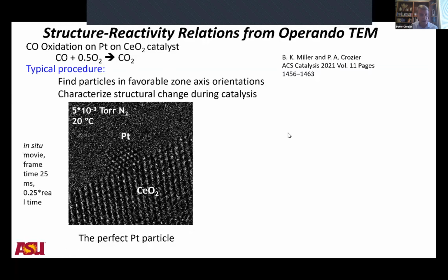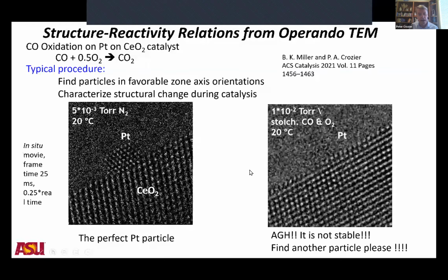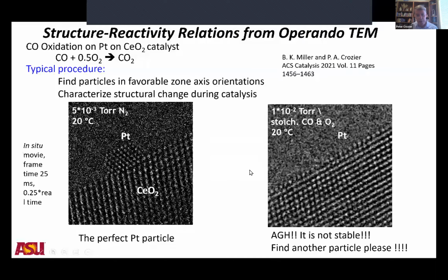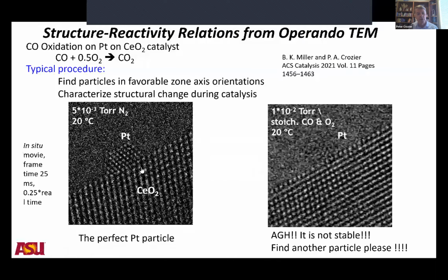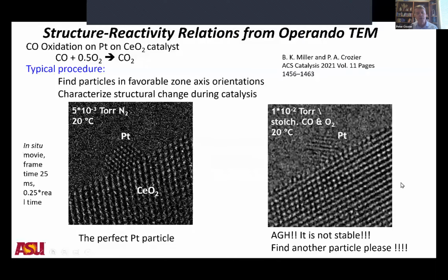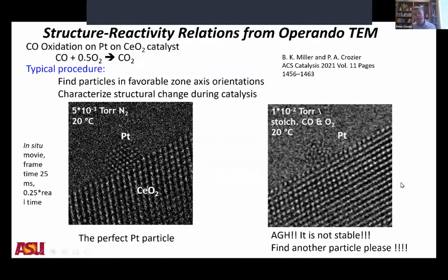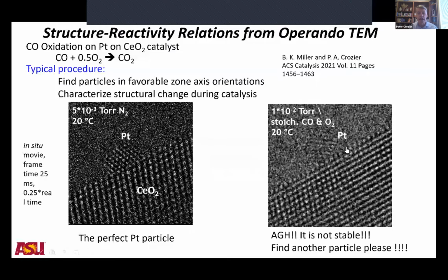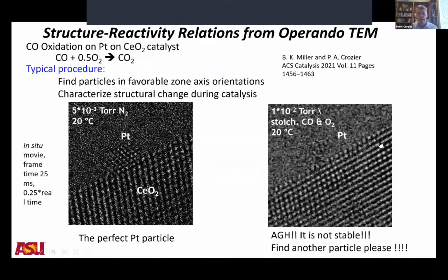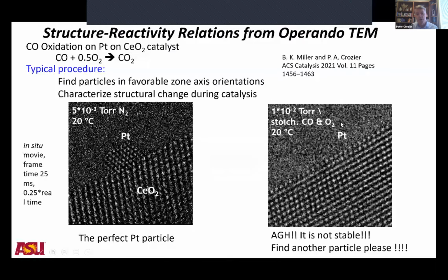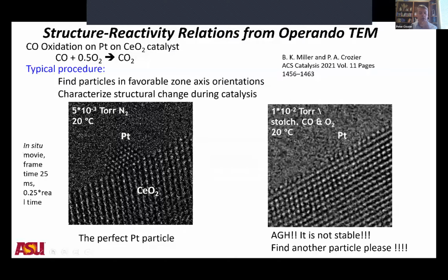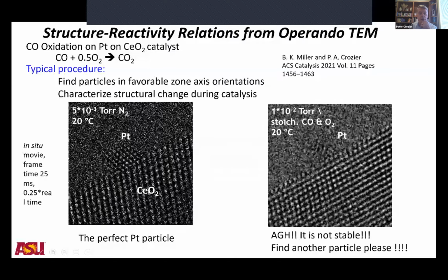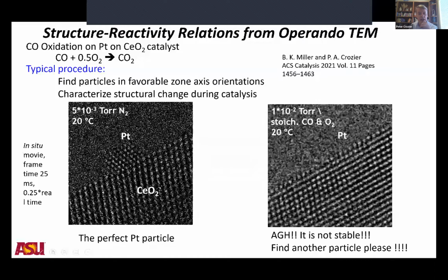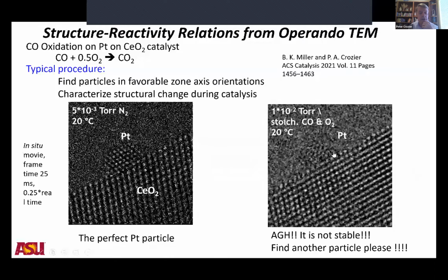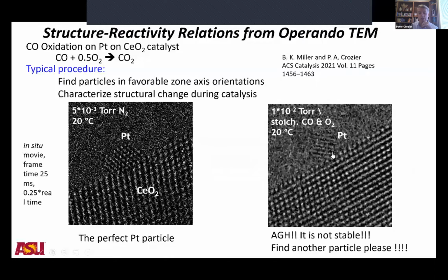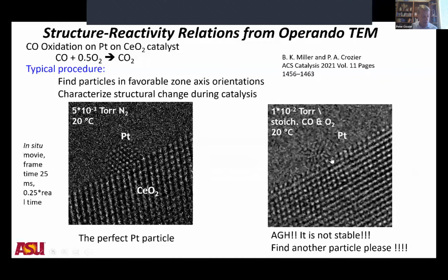And then you would let in the reacting gases. And this is actually very often what happens. You start off with this perfectly oriented particle, and then when you change to the reaction conditions, the sample tilts or moves, and you can see this is exactly the same area. In the presence of CO and oxygen, the platinum nanoparticle is no longer stable. Electron microscopists have seen this for years, and we often just say, well, this is not a stable particle, we'll just move on and find one that's stable.